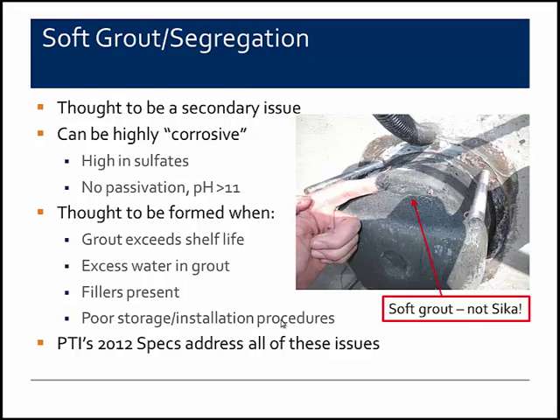And so you end up with steel that crosses this interface from the hardened grout to the soft grout being very well passivated on one side and unpassivated on the other, and that leaves the steel extremely exposed for corrosion without regard to the presence of chlorides.